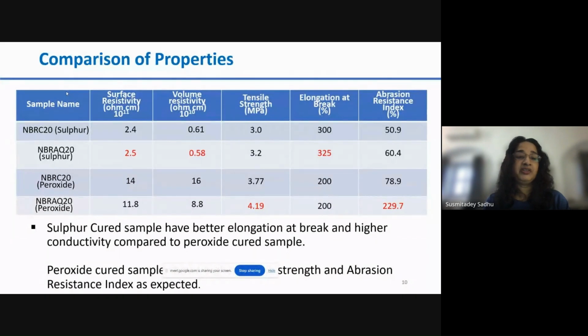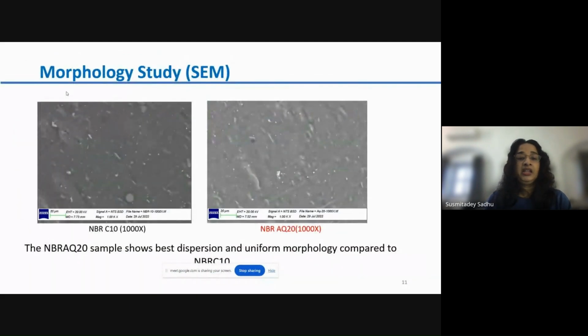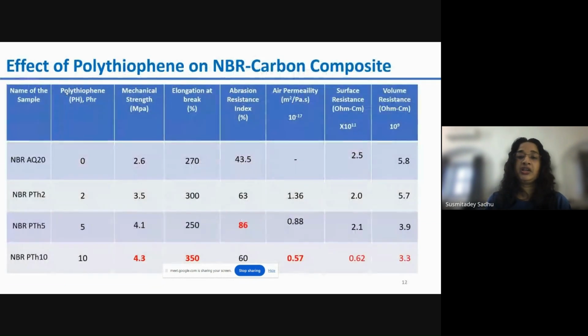So for the rest of the work, we decided to go ahead with the sulfur curing with aqua regia 20% loading. The morphology studies using SEM are compared here. Here we can see that the aqua regia treated carbon black filled at 20% level shows a uniform distribution of the fillers and a good surface finish.